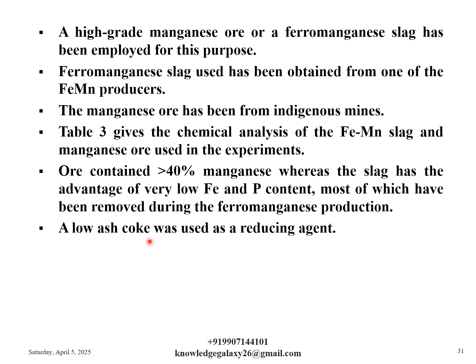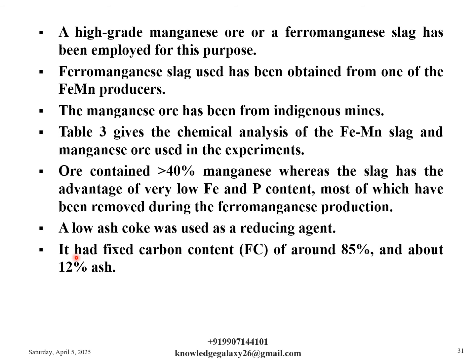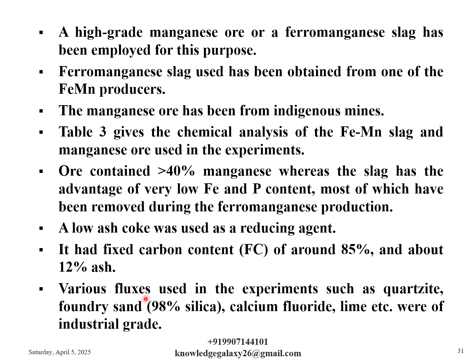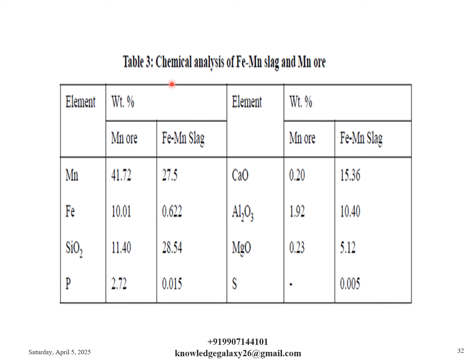A low ash coke was used as a reducing agent. It had fixed carbon content, that is FC, of around 85% and about 12% ash. Various fluxes used in the experiments, such as quartzite, foundry sand having 98% silica, calcium fluoride, lime, etc., were of industrial grade. So this is table 3, which shows the chemical analysis of ferromanganese slag and manganese ore.